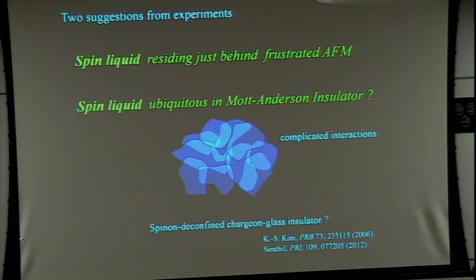So why, in such a situation, is spin liquid-like behavior stabilized? This is a guess. One point is that maybe the spin liquid resides just behind the frustrated antiferromagnetic state. This classical ordered state in the copper chlorine material is a deformed triangular lattice. Its ground state is antiferromagnetic. However, maybe the spin liquid is residing behind the antiferromagnetic ordered state. Maybe that is one conceivable situation. The second one is a very interesting suggestion to me from a theoretical point of view.